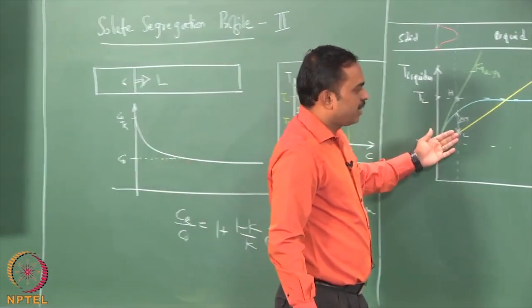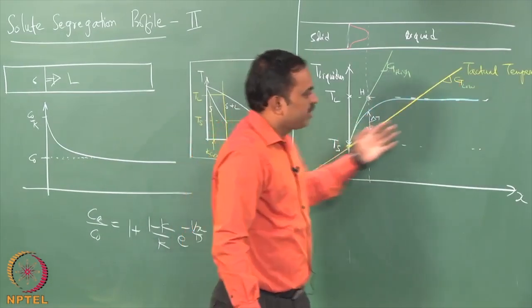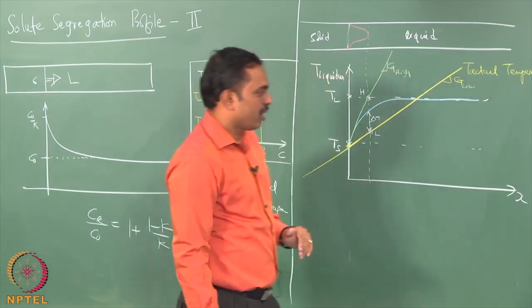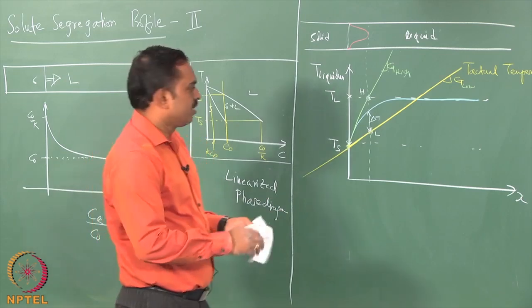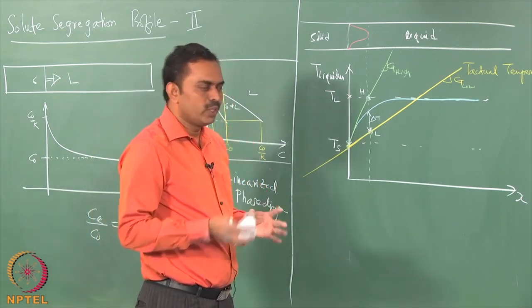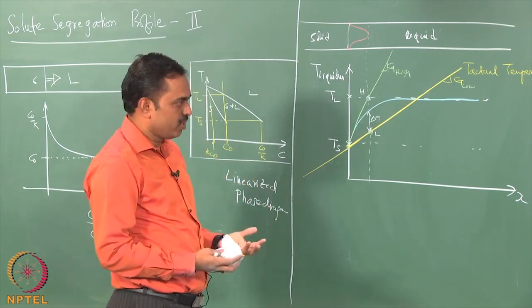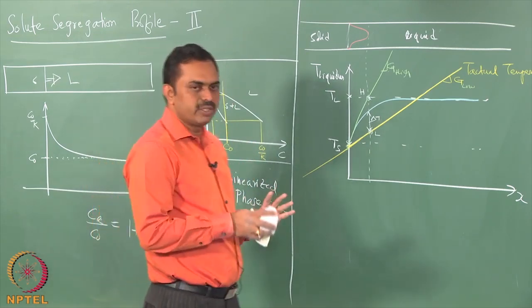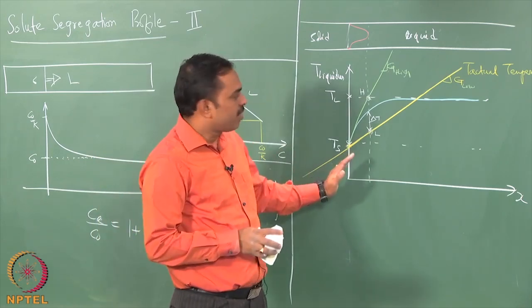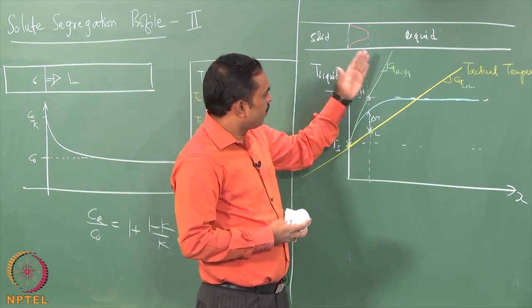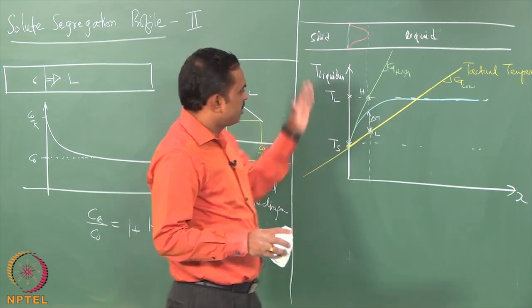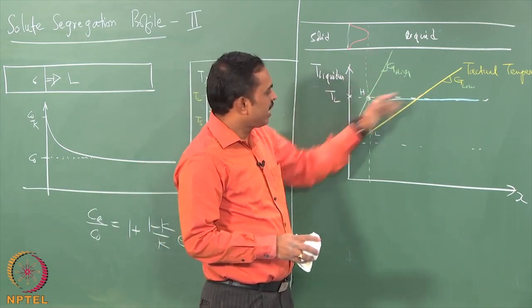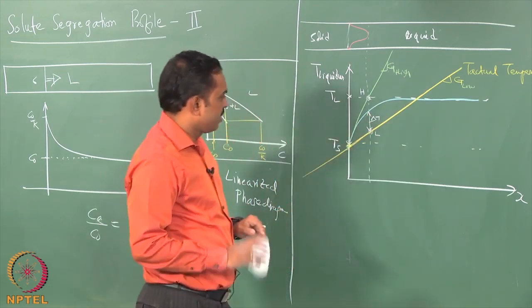This is how we relate the solute undercooling profile to the microstructure. In reality, electron beam welding usually gives columnar microstructure in the fusion zone, while GTAW normally tends to give equiaxed microstructure. This confirms that electron beam welding has very steep gradients giving columnar microstructure, while GTAW has a less steep gradient, allowing undercooling and equiaxed microstructure to form.